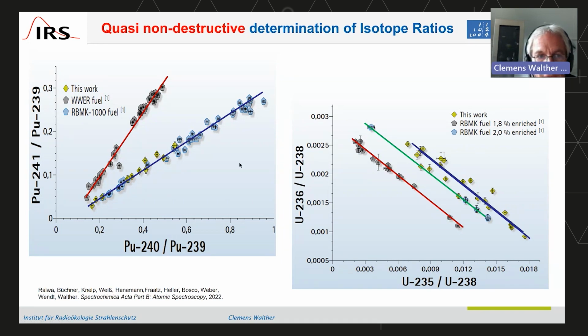So from the left graph, we already know it is RBMK fuel. And from using this isotope ratio, we can even tell, was it 1.8% enriched in the beginning, or was it 2% enriched in the beginning? This red line here is the 1.8 enriched, and this line here with the blue symbols is the 2.0 enriched, and we know that all our data points are 2.0 or even a bit higher.